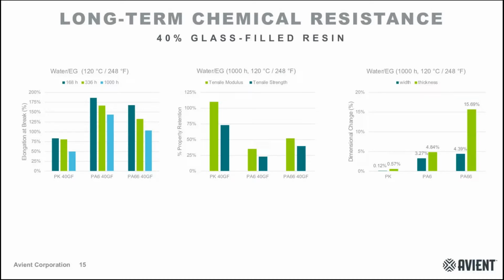Another slide looking at the long-term chemical resistance, in this case, 30% and 40% glass-filled material, again, looking at nylon 6 and 6,6, but testing against water ethylene glycol mixtures. That's another name for antifreeze. And again, looking at long-term 1,000-hour data at 120 degrees Celsius, 248 degrees Fahrenheit. Again, polyketone chemical resistance is excellent even at these elevated temperatures. The glass-filled samples show better property retention and lower dimensional change as compared to these two resins.